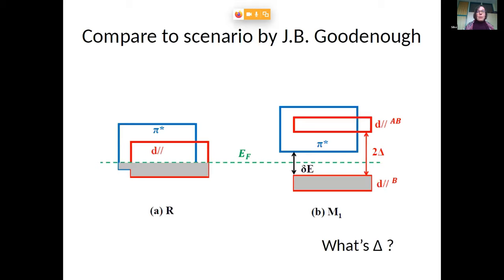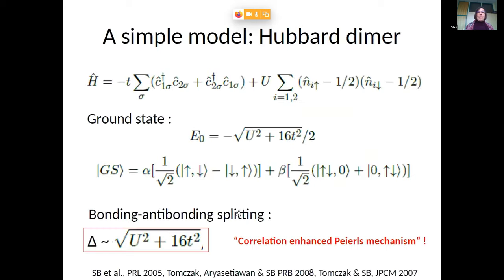Okay, so now let's get back to Goodenough, because as you saw, this was actually very close to what I've shown you before. And you have the bonding, anti-bonding splitting, you have the EG pi states. But of course, you can ask the question, so what is now indeed the bonding, anti-bonding splitting? And for this, we made a little model in the dynamical mean field treatment. Quite naturally, it drops out that what you should investigate is this two-site problem, which you can, in zeroth approximation, if you forget about the bath, consider as a Hubbard dimer problem just for the A1g state now. And this thing is exactly solvable.